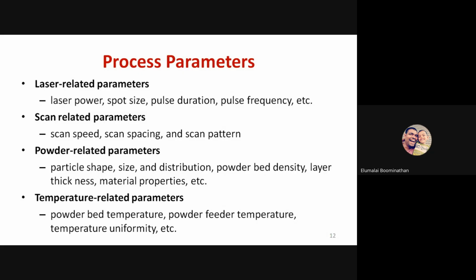So, in the laser related parameters, the laser power is the main thing. If the laser power is too low, we get lack of fusion. Powders won't get fused together, and the particles don't melt properly. And if the laser power is too high, we risk keyhole porosity, where excessive vaporization creates gas bubbles inside the layers. And about the scan speed, again the same. You have to optimize the scan speed. Too fast, bonding is too weak, and too slow, overheating occurs.